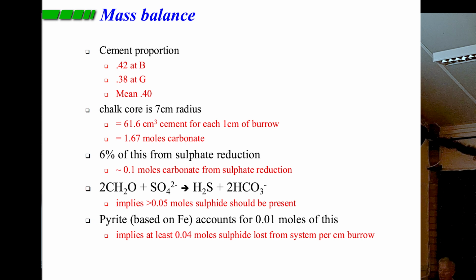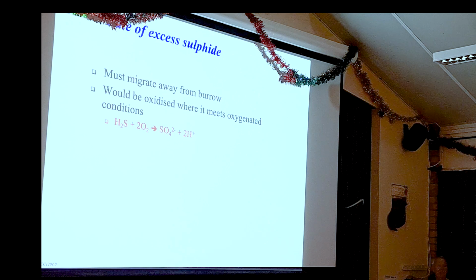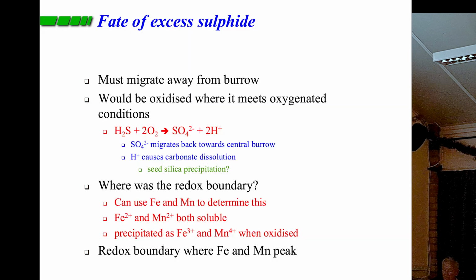Pyrite iron that's there is actually 0.01 moles. In other words, we've lost a lot of sulfide. It's disappeared. It's not present. So where has this excess sulfide gone? Well, it must have migrated away from the central burrow, because that's where the sulfate reduction was occurring. And we know that as we go out, eventually we'll change from sulfate reducing conditions to oxygenated conditions as we move away.